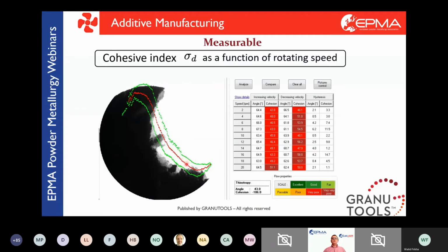So we can measure a cohesive index at each speed. For this powder, which is flour, the cohesive index at 2 RPM is 42.8. From experience, I can tell you 42.8 is not good. If you want to use a powder in an additive manufacturing process, you need to be between 10 and 20, depending on the geometry of your machine and your recoater. Between 10 and 20 is a good value.